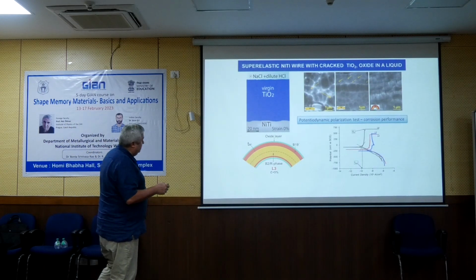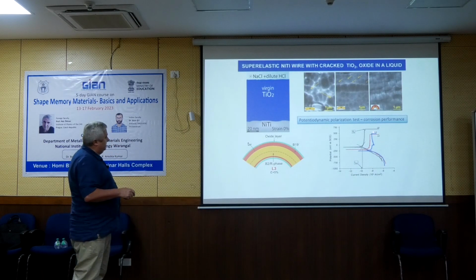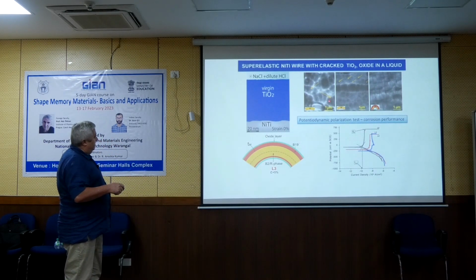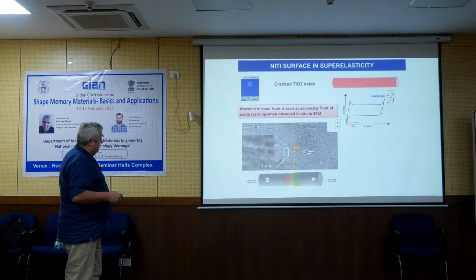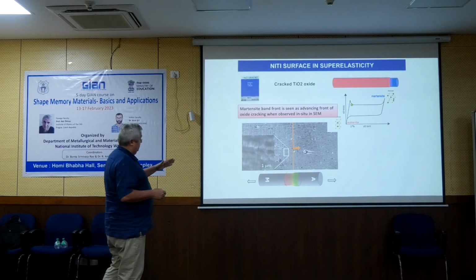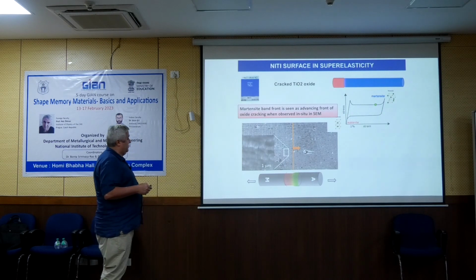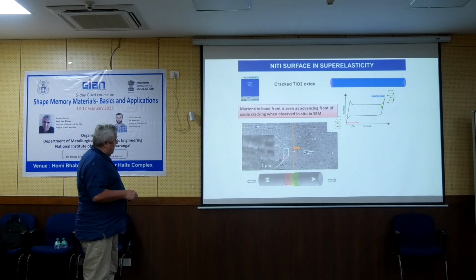I already said that when we bend the wire, the oxide layer will crack. So we performed some experiments on the bent wire with cracked oxide, and it has a somewhat different response in potential and current density electrochemical tests. But I already said that these measurements, simply the response from them was negative, and we had this problem with the oxide which is cracking.